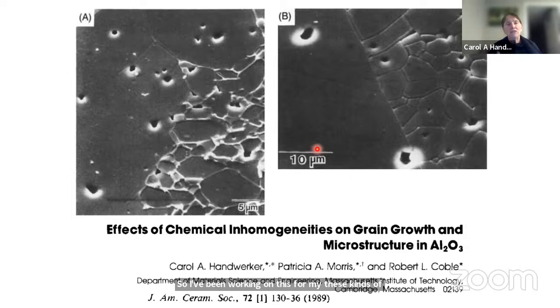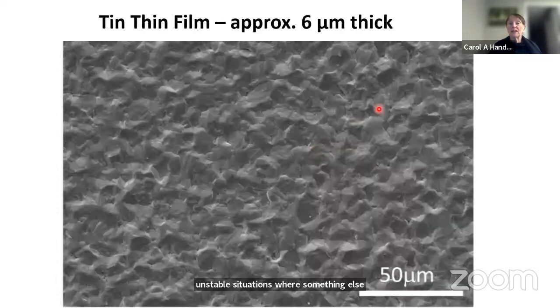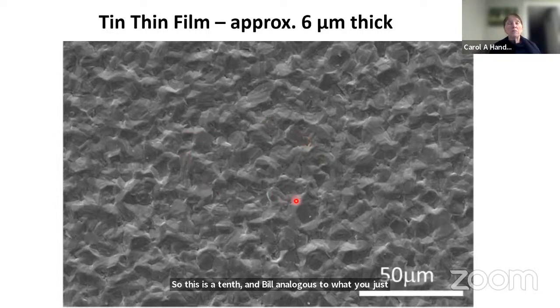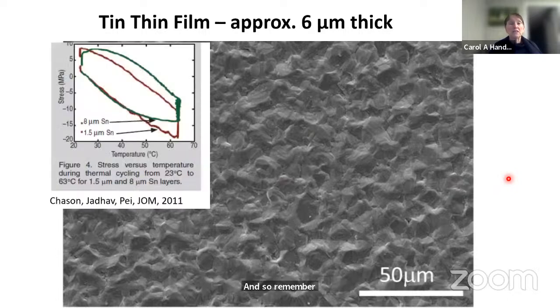So not just the average behavior, but also these very unstable situations where something else happened. So this is a tin thin film, analogous to what you just saw for the polycrystalline ceramic. This is the top surface of a tin thin film. And so you can see individual grains and grain boundaries, and surfaces are not flat. And so when we put these films under stress, something unusual happens. And so remember the size scale, that's 50 micrometers.